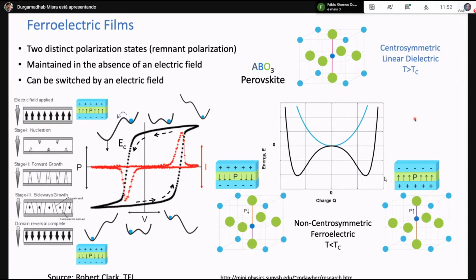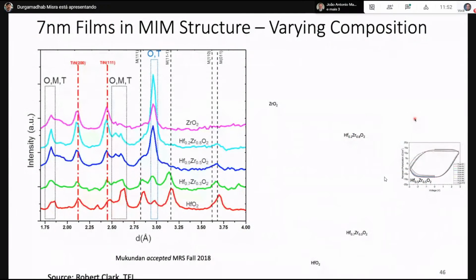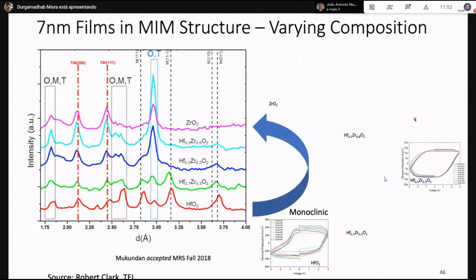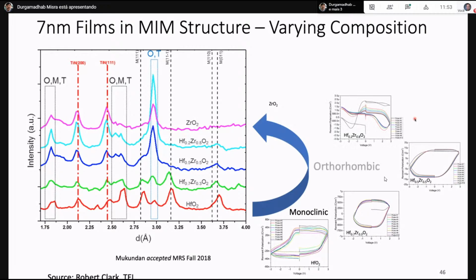There is a lot of modeling and understanding still going on. If you look at the crystallization, the XRD characteristics, you can see the monoclinic phase if you have a certain percentage of hafnium zirconium oxide. It goes to the orthorhombic phase, which is this one and has the highest polarization. This is the 50% of zirconium in hafnium oxide, and that gave the best result. That's why we saw these funny and interesting results in our IV characteristics.